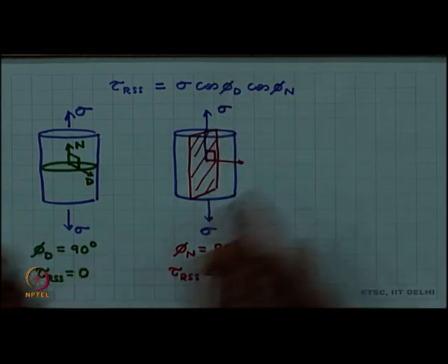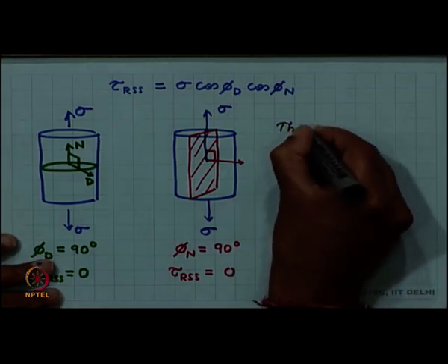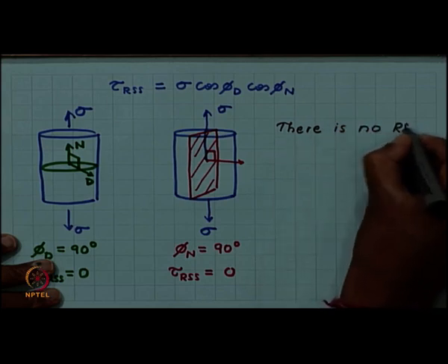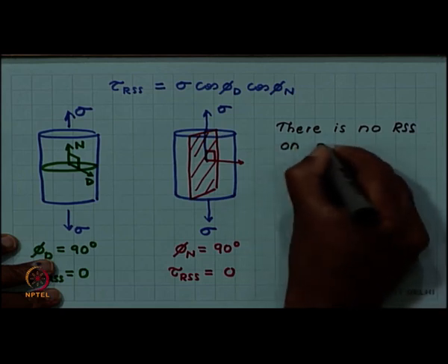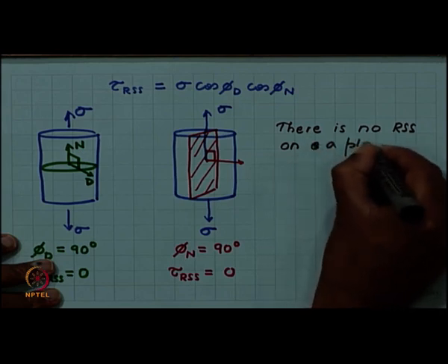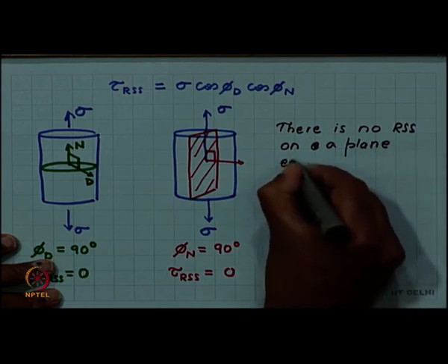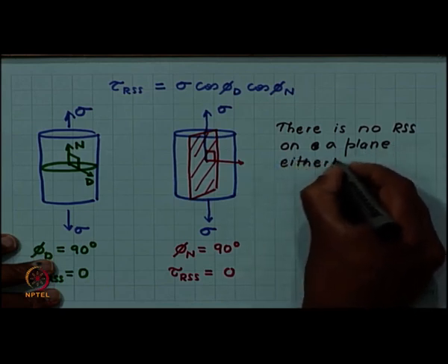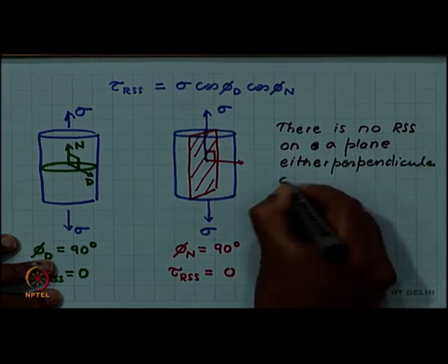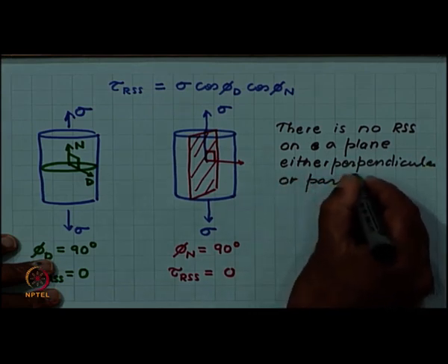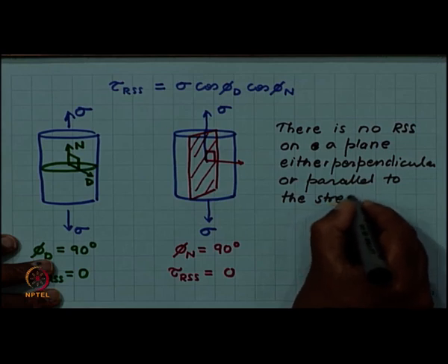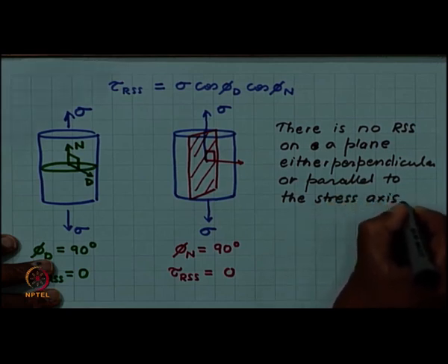So, let us note down this: there is no resolved shear stress, no RSS, on a plane either perpendicular or parallel to the stress axis.